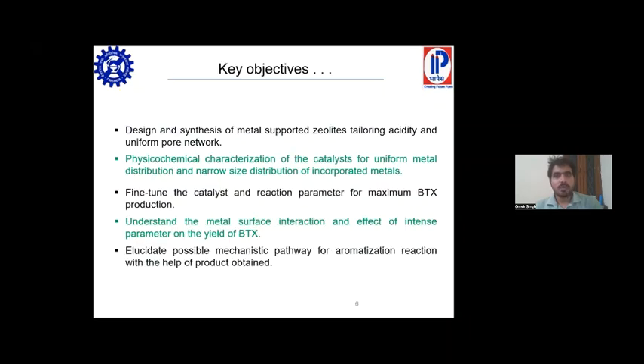Our key objective is to synthesize different metal supported zeolite catalysts, then do physiochemical characterization of the prepared catalysts via several instrumental techniques like XRD, BET, SEM, TEM, TPD, to know the metal support interaction and how much acidity is in the material. Then do the catalytic reaction at high temperature and atmospheric pressure, understand the metal support interaction, and optimize the reaction parameters to know at which temperature and LHSV we get good conversion and aromatic selectivity. Then propose a mechanism pathway of how isopropyl alcohol can be converted into aromatic hydrocarbon.